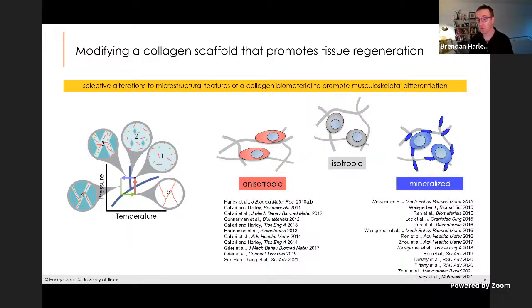So we did a lot of work over the last 20 years to develop processing conditions by which we can create really spherical and uniform pores, ellipsoidal and aligned pores to make anisotropic structures, and to add in other ingredients such as mineral nanocrystallites to mimic bone. You know, bone that we see in our body has a lot of collagen, has a bunch of mineral in it. So we tried to develop porous scaffolds that would have the same composition as the bones in our body.